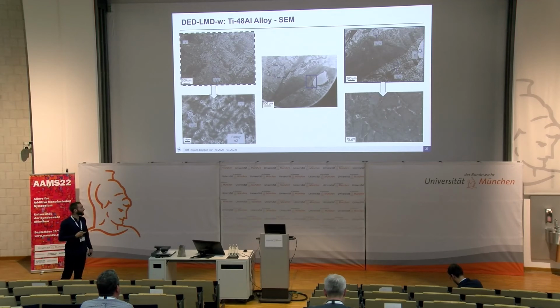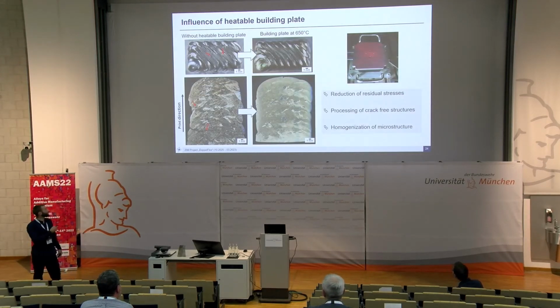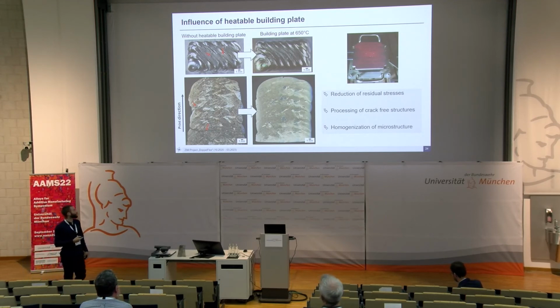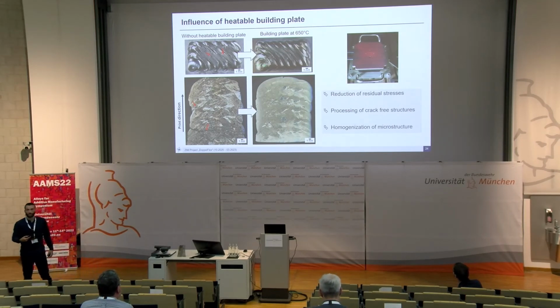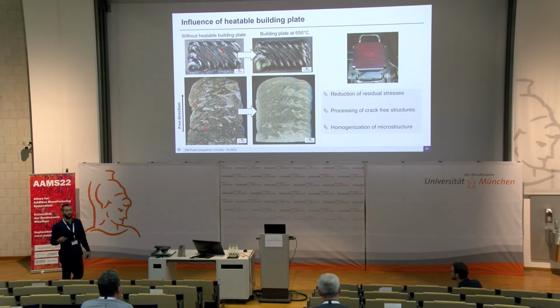When we got our heatable building plate, we thought maybe that's going to change things. Here you can see the influence of the heatable building plate. This is the part without it. We see a lot of cracks, even in the hatching patterns. With the building plate at 650 degrees, we get rid of these cracks, even on the bigger scale. We also have a reduction of the residual stresses. You can imagine it's like an annealing process if you slowly cool the structure down. So we can process crack-free structures. One side effect is that we got a bit of homogenization of the microstructure, so we get a lot more lamellar structures in there.